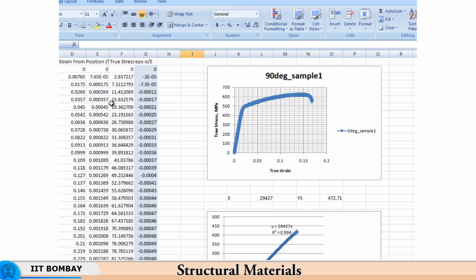Now, the logic here is that all grains do not yield at once, and therefore some of the grains reach yield point, but few other grains might not reach yield point in a polycrystalline material. Most of the materials we use are polycrystalline in nature, each grain is surrounded by many other grains, and due to that there is a constraint that is imposed on a grain due to surrounding grains. So, now what happens is, if the surface grains reach the yield point, the interior of the sample has not reached the yield point yet, because the yield point of that is much higher compared to the yield point of the surface grains. So, now you have surface grains which might have yielded, but the interior of the sample which has not yielded.